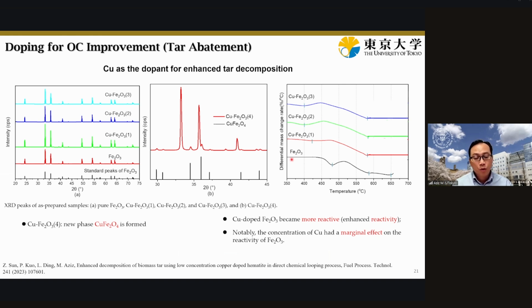But we also need to be careful here. Once we increase the ratio of copper during the doping, sometimes copper also leads to agglomeration and sintering. So that's also something we need to consider when we are doping copper and other intermetallic materials into the oxygen carriers. For reference, usually for the reduction, the temperature is about 800 to 950 degrees Celsius. So that's pretty high, and some metals actually sinter at those temperatures. So in our case, the question is how to minimize the amount of doping materials like copper, nickel, etc., while we are trying to improve the performance of the oxygen carrier itself.